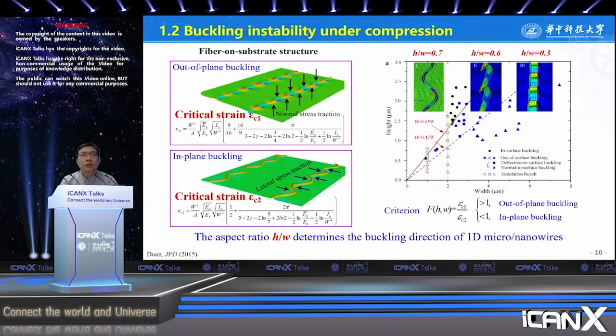In stretchable electronics, buckling of microstructures under pressure is inevitable. There exist out-of-plane buckling and in-plane buckling. Although there exist studies with a critical understanding of the buckling behavior, including the critical strain for buckling and the wavelength and the amplitude of buckled structures, the left two figures show two kinds of buckling: out-of-plane buckling and in-plane buckling. What inherently controls the competition between the two buckling modes?